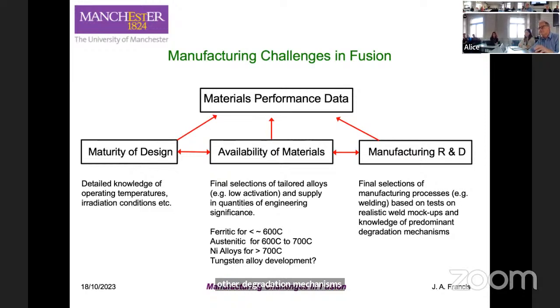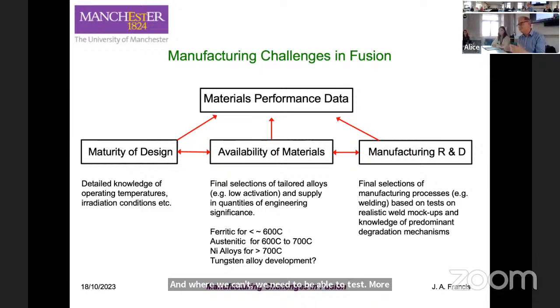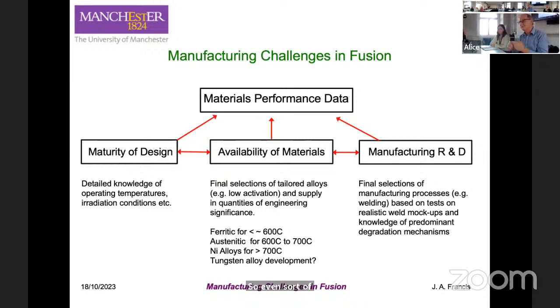Now, each one of those materials will have a different joining solution, and will have a different range of microstructures that are produced at joints. And what we need to do is, ultimately, I agree that we need to eliminate welds as much as possible, but we won't be able to avoid all of them. And where we can't, we need to be able to test mock-ups as best we can before we consider putting them into service. So even more tightly specifying what we're aiming for in terms of joining is going to be a huge help.